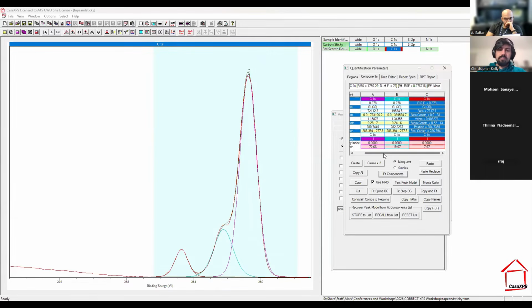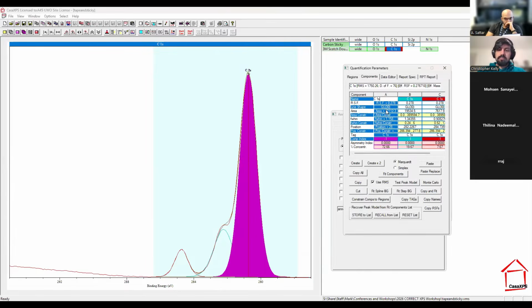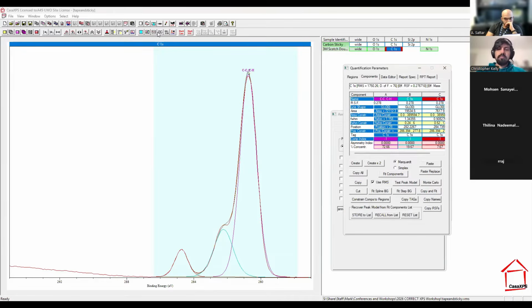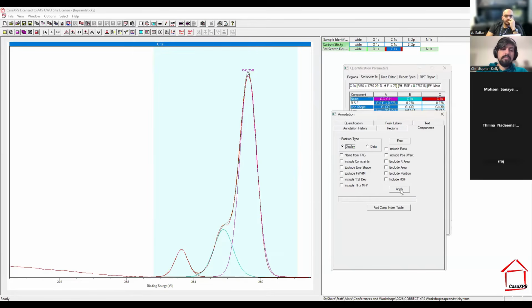You can go in and you can change the labels of that. So this we know is carbon bound to carbon, carbon bound to hydrogen. So that's our aliphatic backbone of whatever this material is. It's basically a piece of Scotch tape is what we're looking at. If we put our labels of our components on, you can see we have 3 peaks with varying widths.